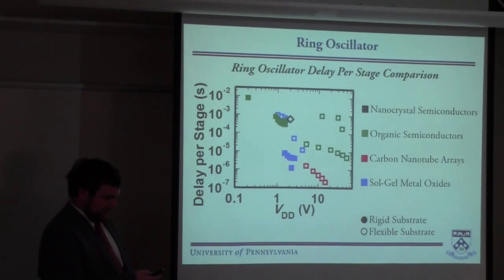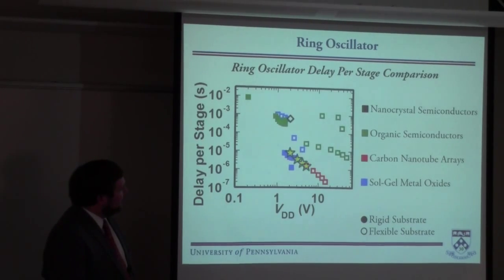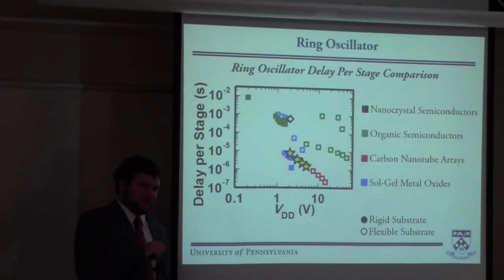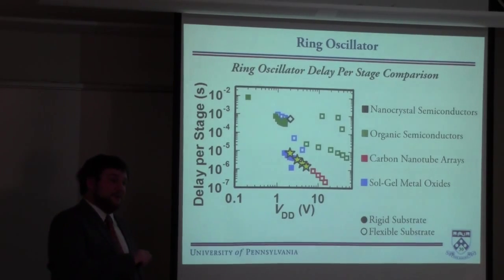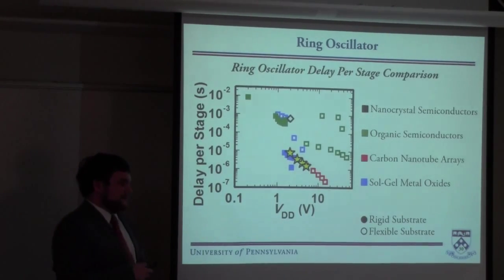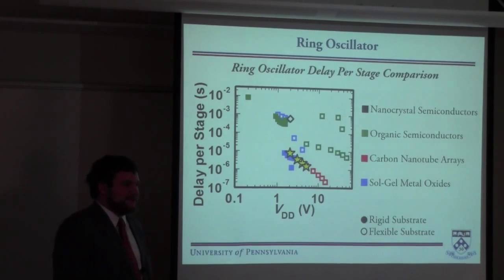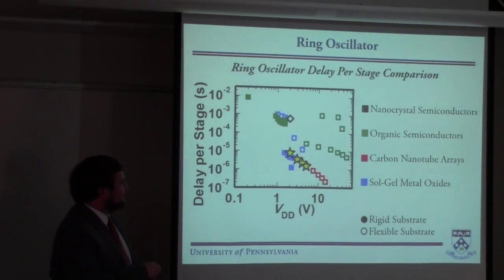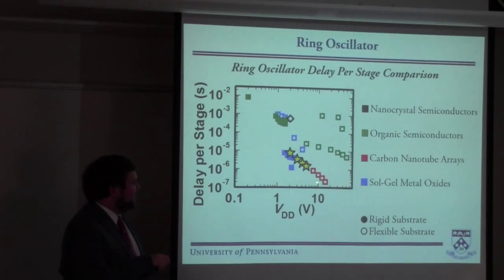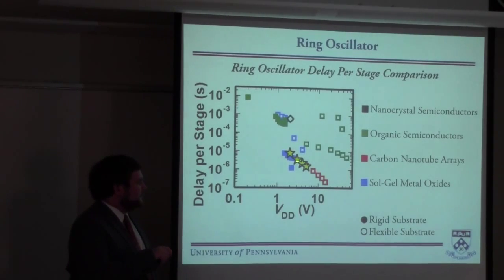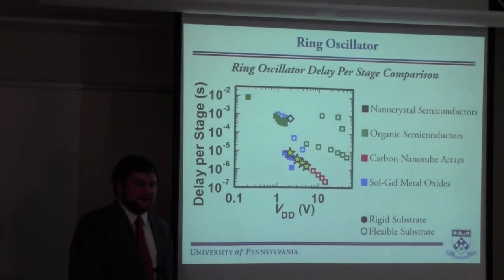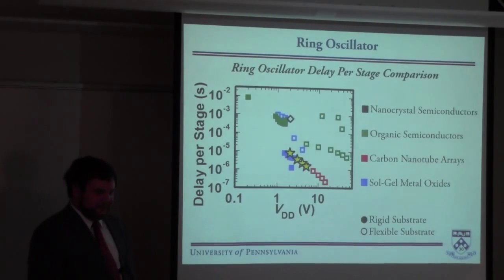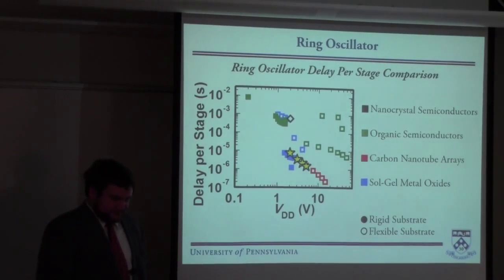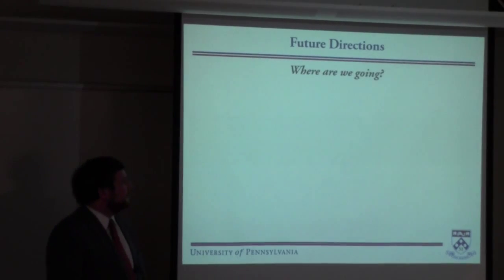And the devices that we built fit right in there. There are some sol-gel metal oxides that are doing a bit better, but they have to be on rigid substrates because they need annealing temperatures upwards of 500 C to make some of these metal oxides. So that's why those are all on rigid, but these are our flexible substrate devices fitting in right where we wanted them to.